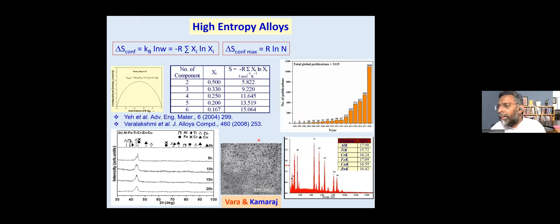So there are two ways of making these alloys. One is to take all these elements, five or six elements, in equal proportions, let's say, melt all of them, and then cast them so that you get an alloy casting. The second way is I can take all these elements, put them into something called a high energy ball mill, and grind these powder particles in such a way that you get an alloy powder at the end of it, after some hours of ball milling. So here you get the alloy in powder form, whereas in the other technique, which is called the casting technique, you get the alloys in a rod form or in an ingot form or something like that.